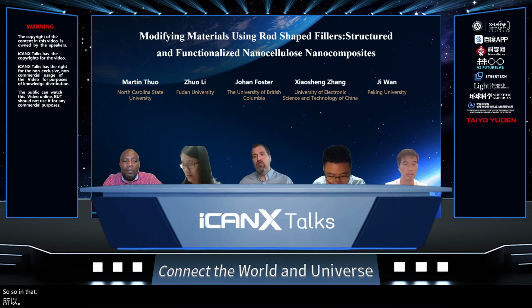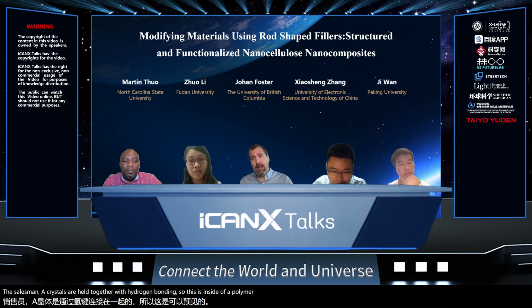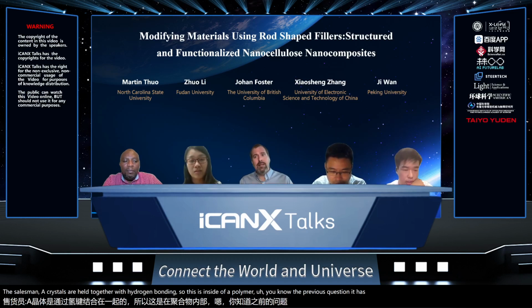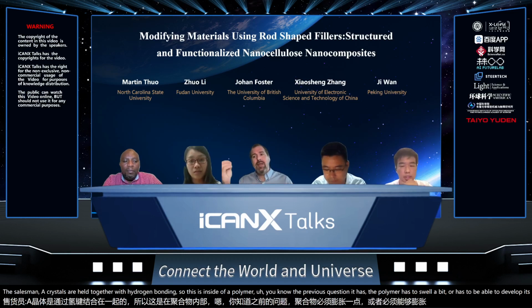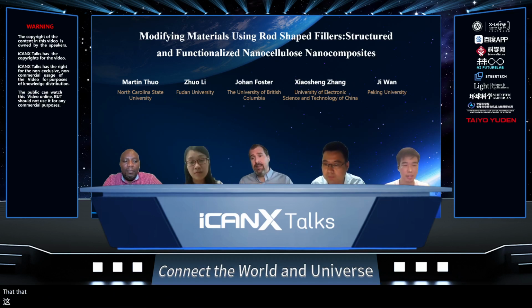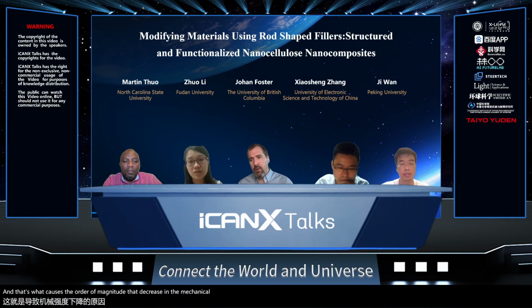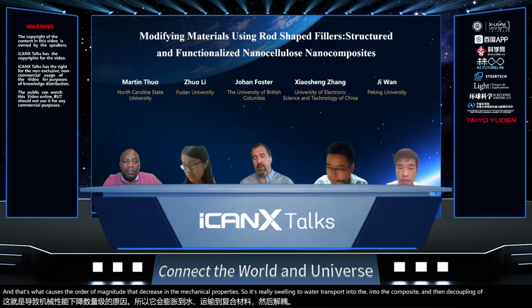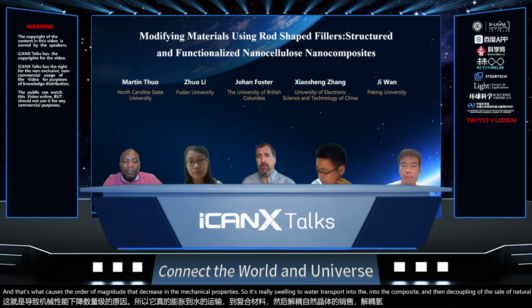So in that case, in the dry state, so outside of the body, the cellulose nanocrystals are held together with hydrogen bonding. So this is inside of a polymer. To the previous question, the polymer has to be able to swell a bit. When we implant it inside of the body, so you push it into the brain, that composite takes up a little bit of water, decouples the interactions between the cellulose nanocrystals, and that's what causes the order of magnitude decrease in the mechanical properties. So it's really swelling, so water transport into the composite, and then decoupling of the hydrogen bonds between the cellulose nanocrystals.